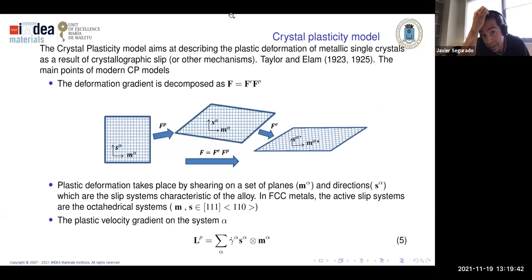The crystal plasticity model, as I told, is just aiming at describing the plastic deformation of metallic single crystals that is the result of crystallographic slip. So it means that one part of the crystal slips with respect to the other thanks to the movement of dislocations. The model was proposed almost 100 years ago by Taylor and Elam in the 20s. Okay, although of course what we have right now has evolved a bit from that moment, but the original idea of these shears depending on some resolved stress and how this is accommodated from a single crystal to a polycrystal comes from these ages. So the main ingredients of any crystal plasticity model are specified here.